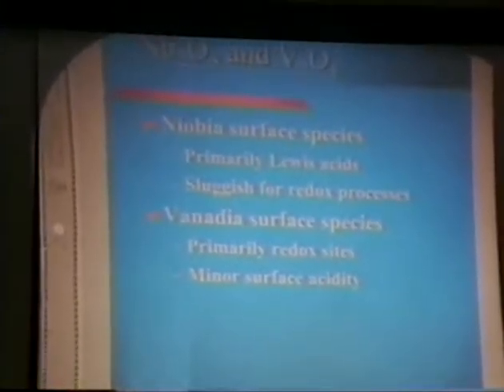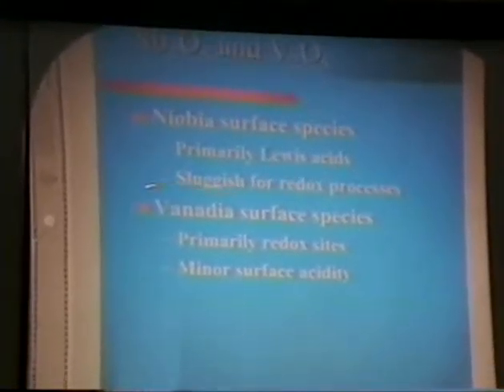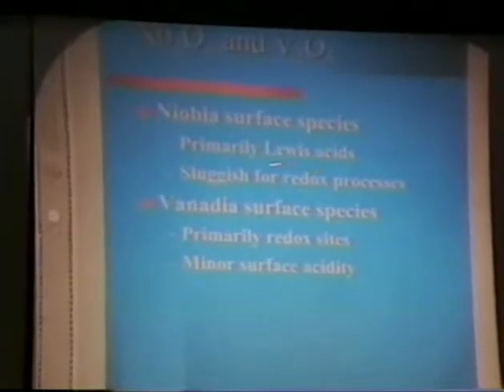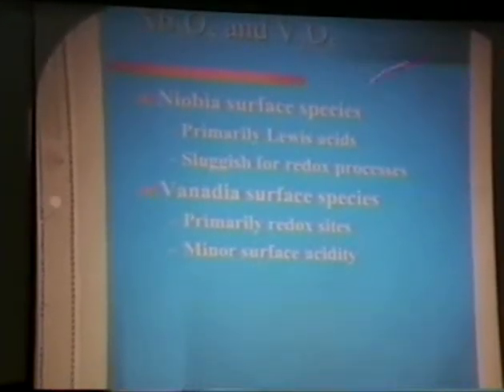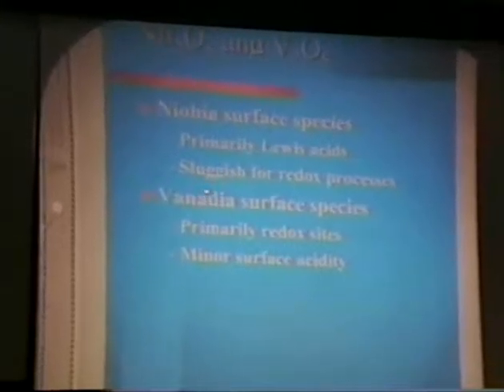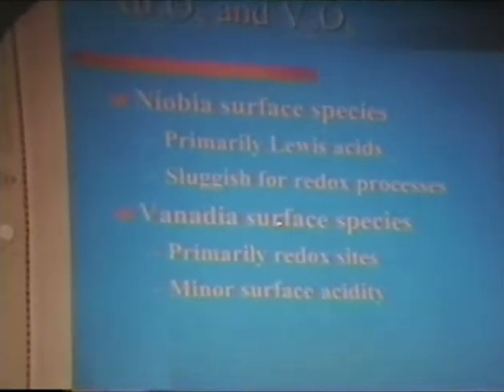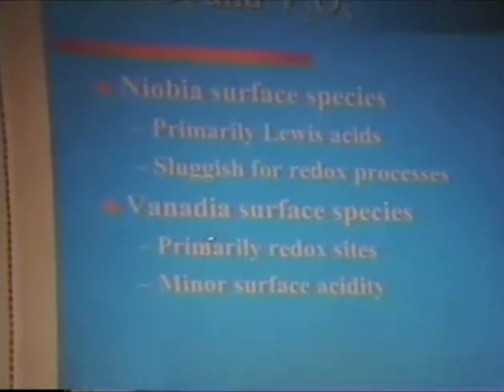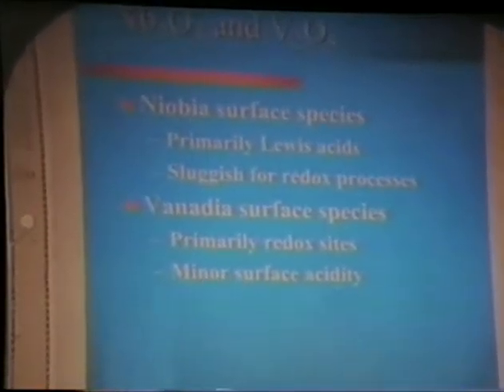Wachs has summarized the performance of niobium in comparison against vanadium in an article that was published in Catalysis Today. I think it was in the March issue. The niobium surface species are primarily Lewis acids. Redox is not one of the attractive features. In contrast, the vanadium surface species are primarily redox sites and may have some minor surface acidity associated with them.